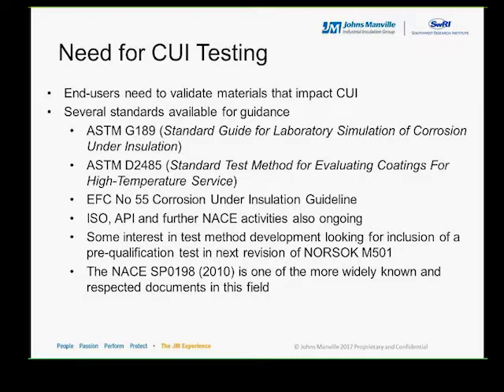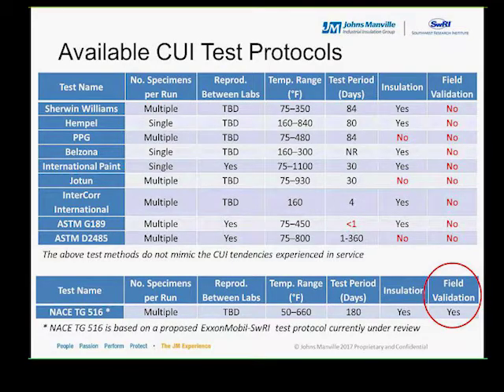Available CUI test protocols. Experience has shown that performance-based qualification of coatings and insulations is more effective at raising performance than compositional standards. The majority of the CUI test methods are not field validated, plus there are either some geometrical issues of the test specimens or temperature limitations, in addition to the lack of insulation in the tests. All that may pose real problems when it comes to mimicking CUI in the laboratory.